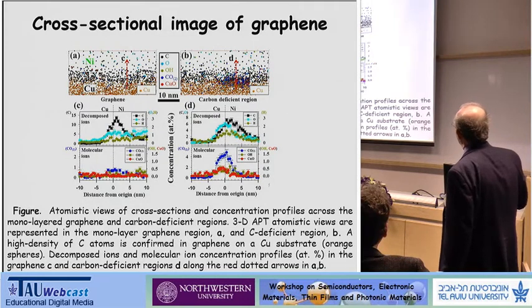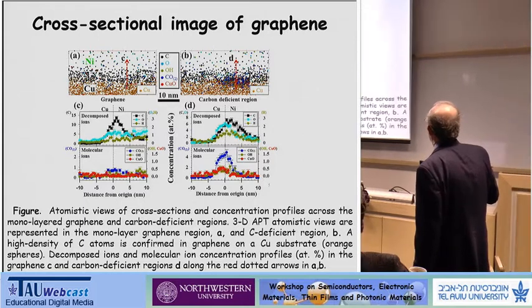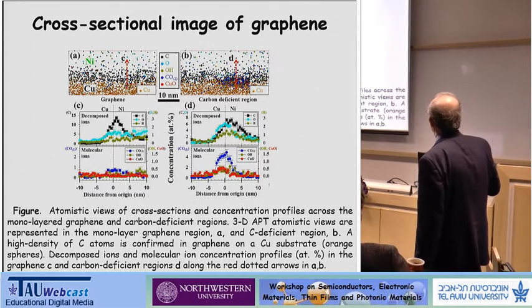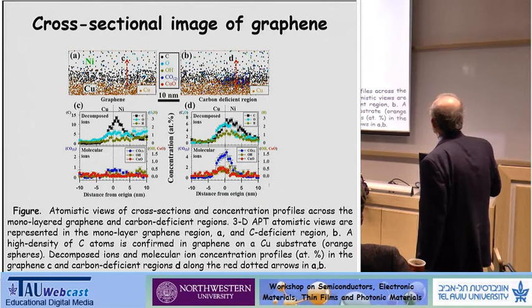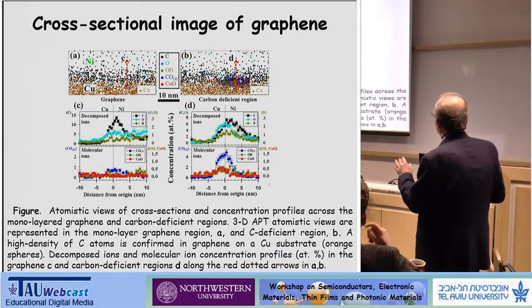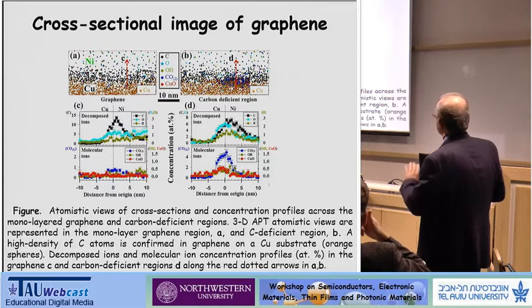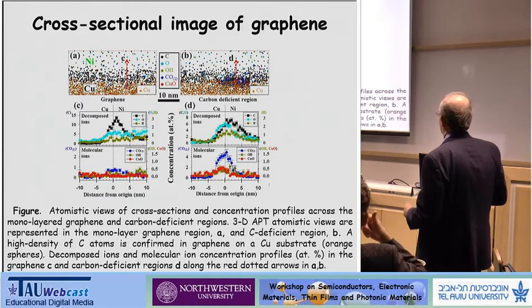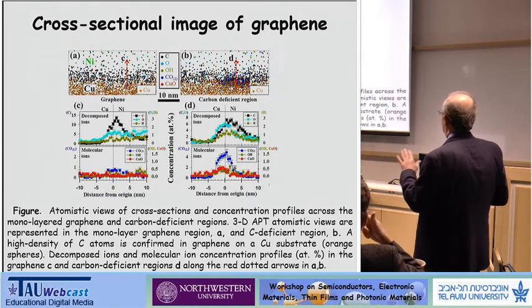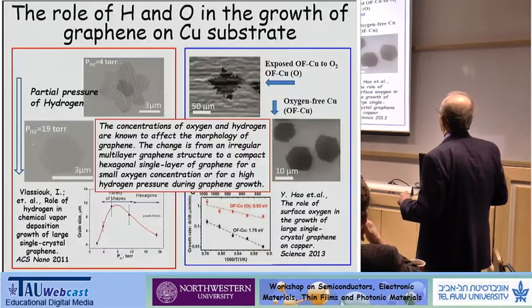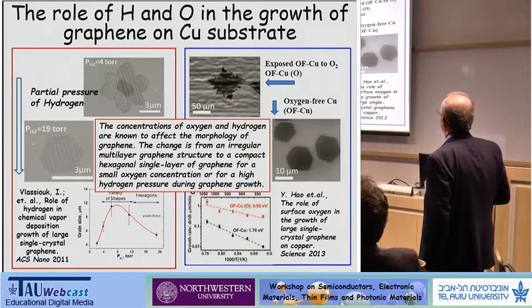If you then look at this region, which is carbon deficient, you can see that the oxygen concentration is much higher, and the hydrogen concentration is much higher. And also, the molecular ions are much more abundant. They have much higher concentrations. So in this way, we have a chemical map of the graphene, both the graphene that's at the right density and graphene that's at a lower density.